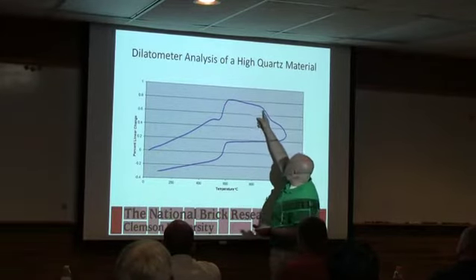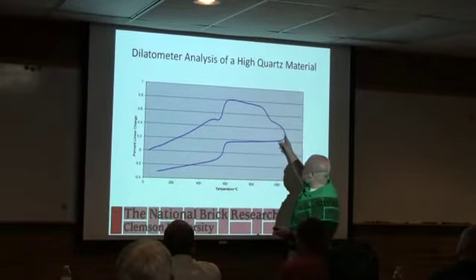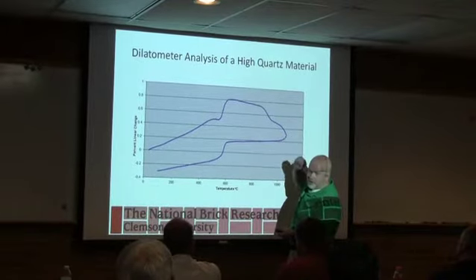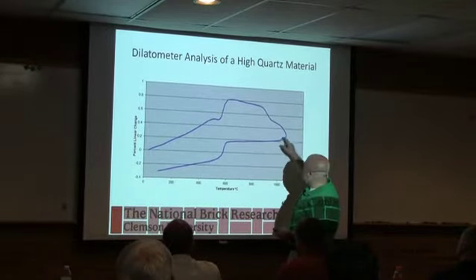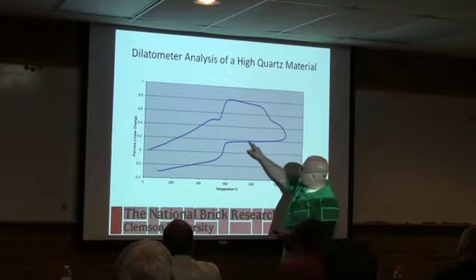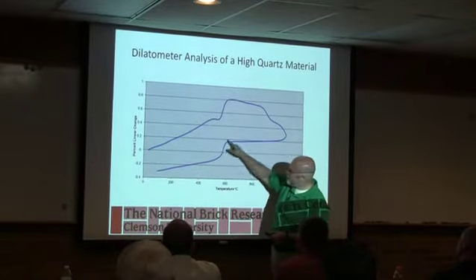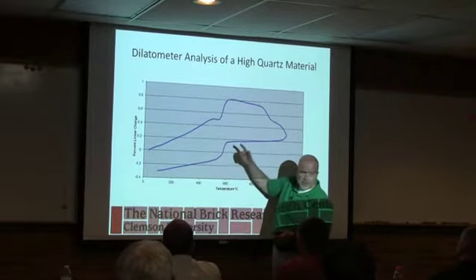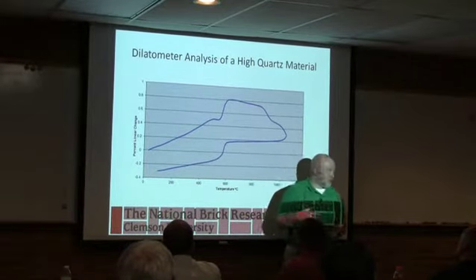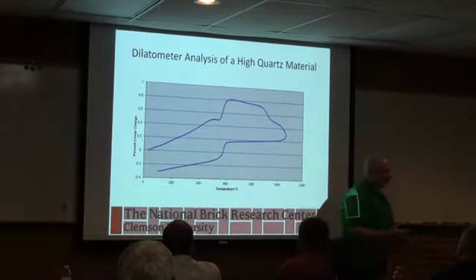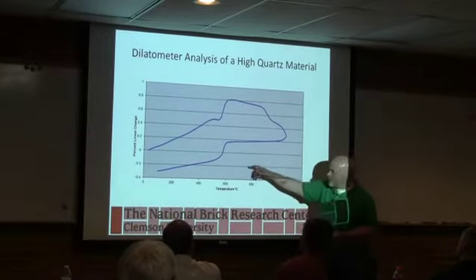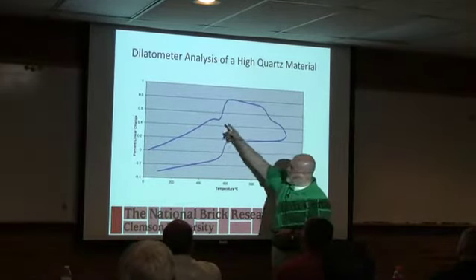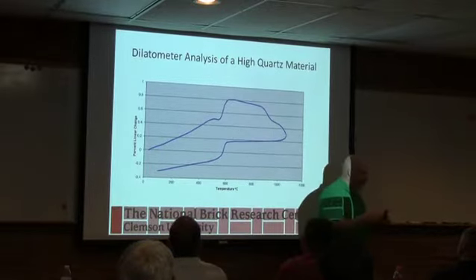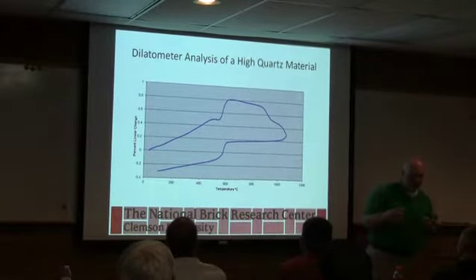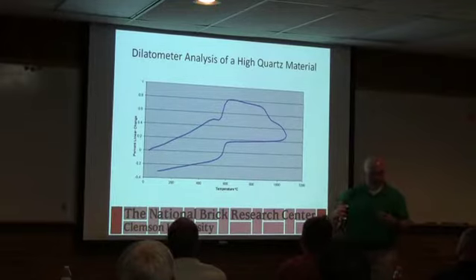And then we come out and we start to make some glass, but in a high quartz material, typically you don't make a lot of glass because they tend to be a little harder to fire. And then you start cooling off, and this is where damage from the quartz inversion, some people call it dunting. Have any of you ever heard that term? Okay, that's what causes dunting right here. On the heat up, we're not so much worried about it because we haven't made the glass yet. The body's a little more forgiving and it can tolerate that expansion.